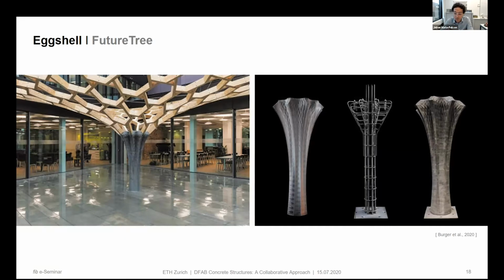That could be like here, 3D printed plastic formwork, but it could be just a tension plastic foil. And here, this is another structure in which, because of the geometry, we could fit the reinforcement inside the 3D printed formwork, and then cast it in with this set on demand process that minimizes the formwork pressure.